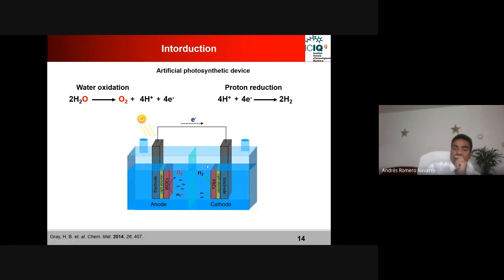So we can convert this proton to hydrogen in the cathode. Another thing that I mentioned before is that we can utilize this proton source, which we get from water oxidation, to reduce CO2 to carbohydrate. Or we can do the reduction of a very inert molecule, nitrogen, to ammonia, and that is very in demand because it is used for agricultural purposes. Haber-Bosch already got a Nobel Prize for synthesizing ammonia, but the conditions were high temperature and high pressure. But we wanted to do it with this artificial photosynthetic device at room temperature and normal pressure, 1 atmosphere. So that was the dream.